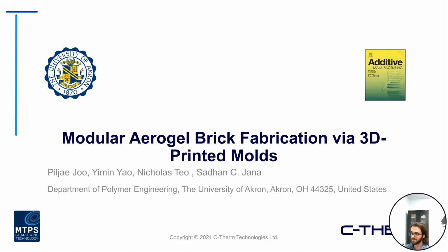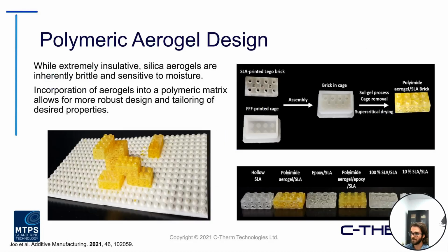And then this one here was a neat one that we found. This is on a brick fabrication using 3D printed technology with an aerogel additive. This is some work coming out of the United States, University of Akron. For any of you who like playing with Legos, or if you have kids that like playing with Legos, you'll get a kick out of this. They basically designed these 3D printed materials with these Lego-like structures. The idea here was that, while very insulative in nature, pure aerogels can be very brittle, damage quite easily, and are sensitive to moisture. So by incorporating the aerogel additive into the polymer matrix in this fashion, you're able to fine tune and tailor those properties to what's needed for your end use.